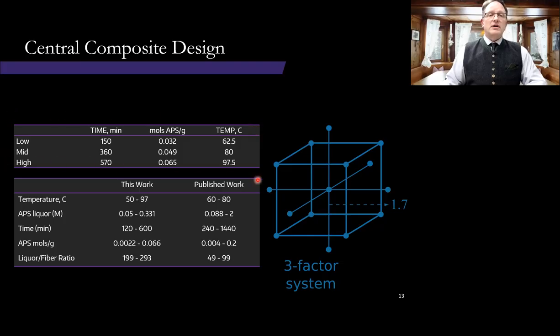This first table are the treatment conditions for our central composite design. In the second table, I have listed here the treatment conditions, the range of conditions that we used during the entire investigation relative to the published work here. And you can see that the range in our work was a little bit broader. And that covers some of the preliminary work we did in order to identify what the right conditions for the central composite design were.